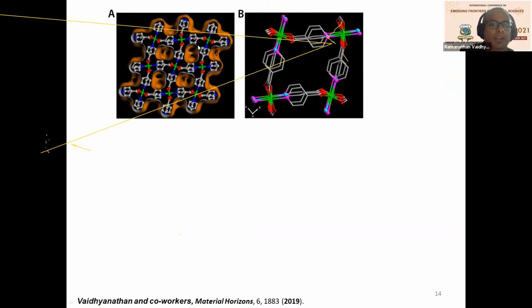This brown color representation I'm showing is what is called a Connolly surface diagram. And you can clearly see the black region, which represents the open pores, is very small in this MOF, which means it is practically non-porous. And if you carefully look at why it is non-porous, the adjacent pyridyl bonded groups are rotated by 90 degrees with respect to each other. They are not staggered, okay? Because of this, they block the porosity in both directions. Think of it like this. If I keep it like this, this direction porosity is blocked by this one. This direction porosity is blocked by this one. So both sides are blocked, and there is not really an openness to the structure. But it is a very stable, beautiful MOF framework.